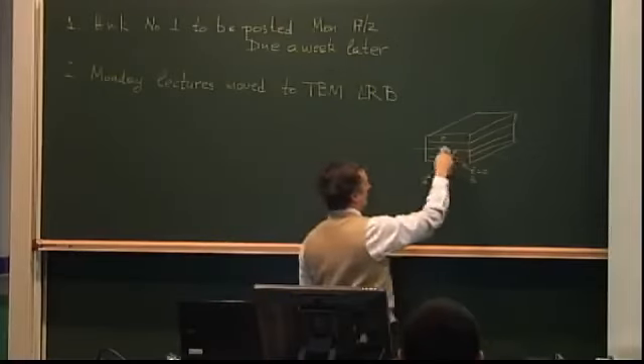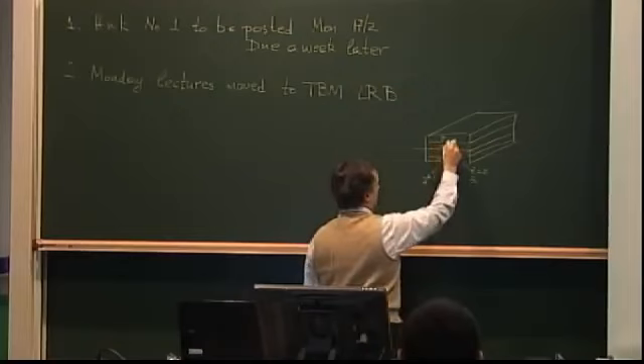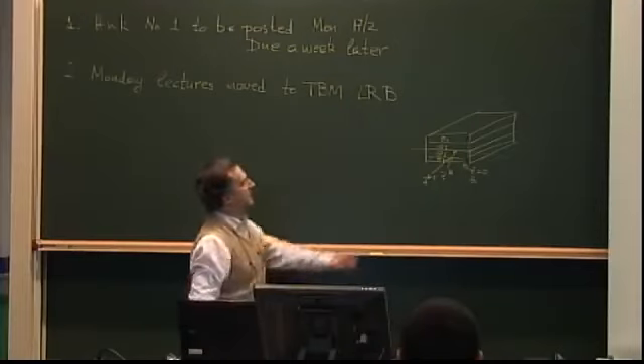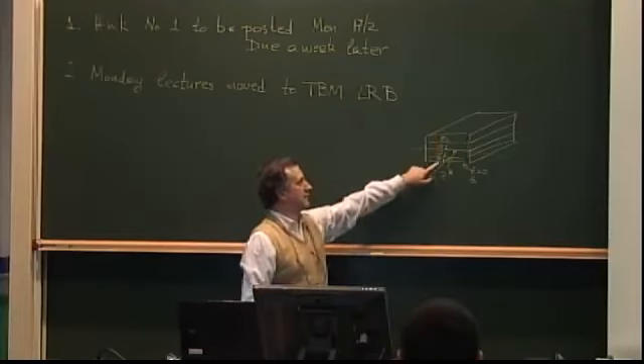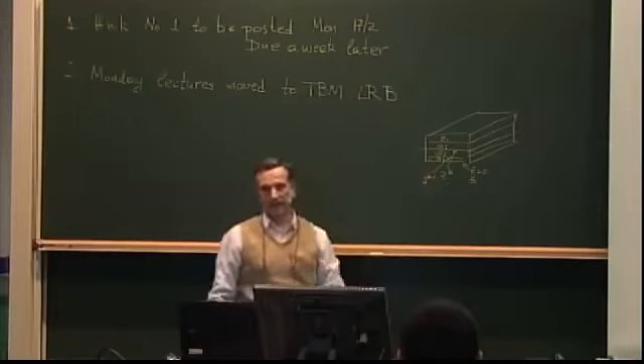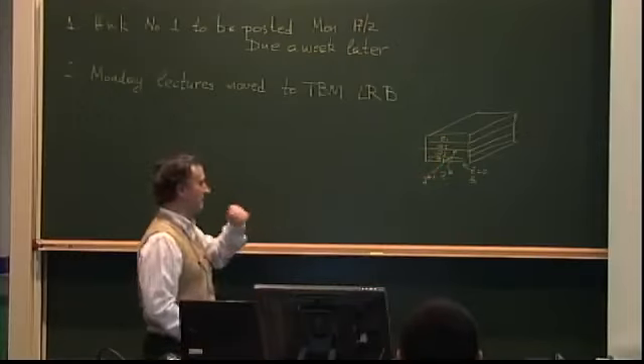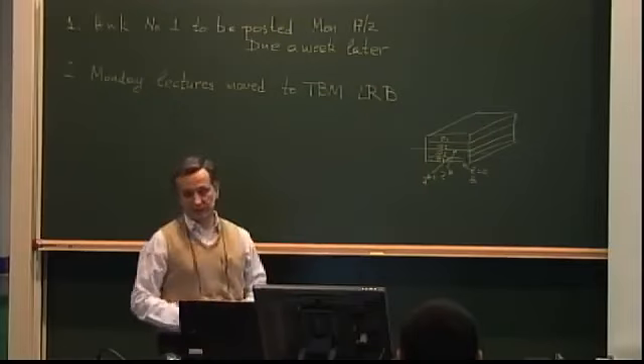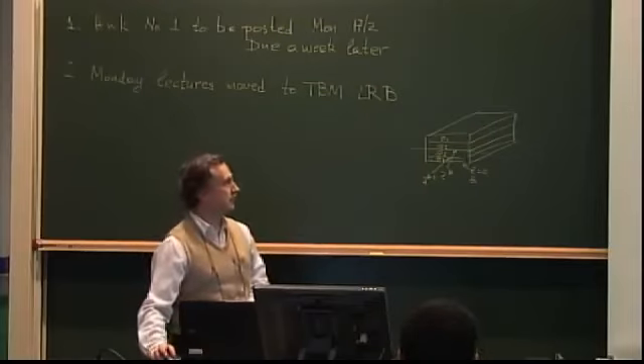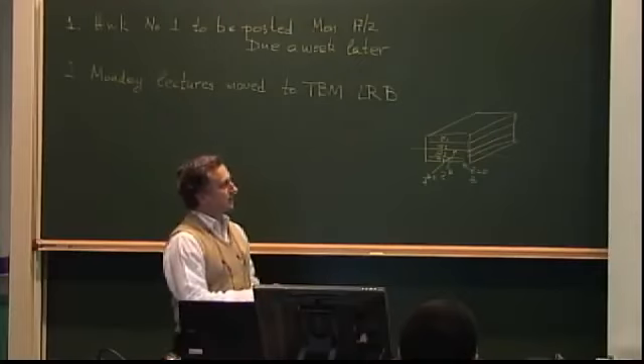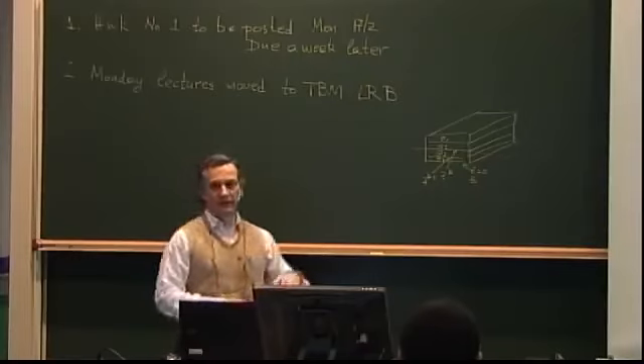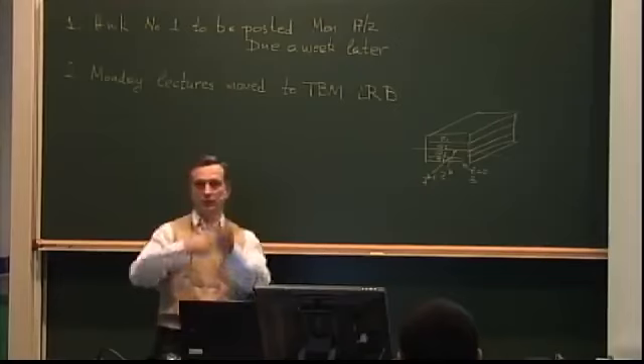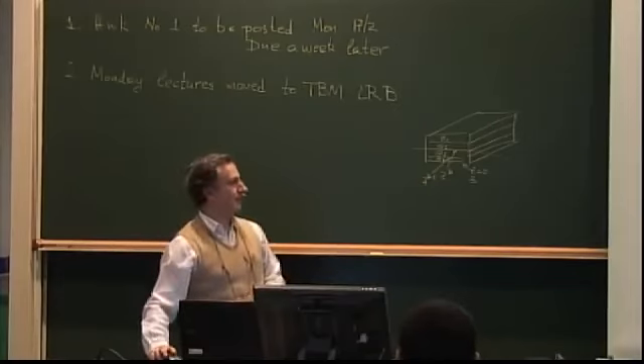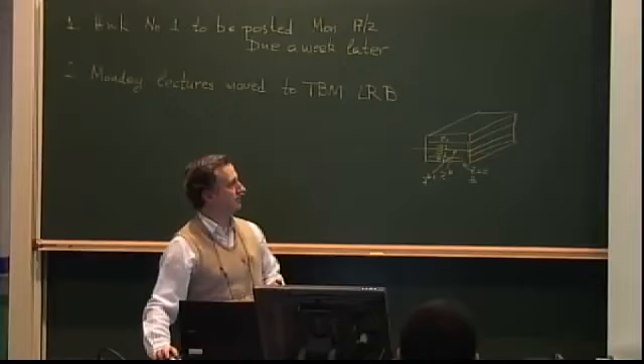So with respect to the mid-plane, this would be a symmetric laminate because the theta 1 at the top ply is the same as the bottom one, and the theta 2 at the ply next to the mid-plane is equal to the one right below the mid-plane. Once you have this, you can show, if you go back to our B matrix definition, that these terms will cancel out, because whatever you get above the mid-plane as a contribution will be cancelled by whatever you get from below the mid-plane. As a result, the B matrix is 0, which simplifies things.